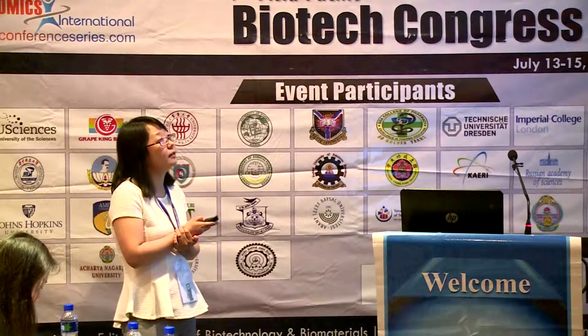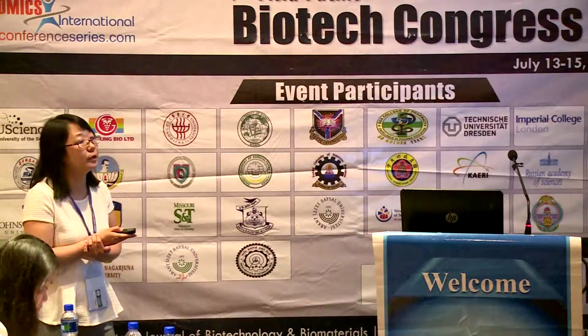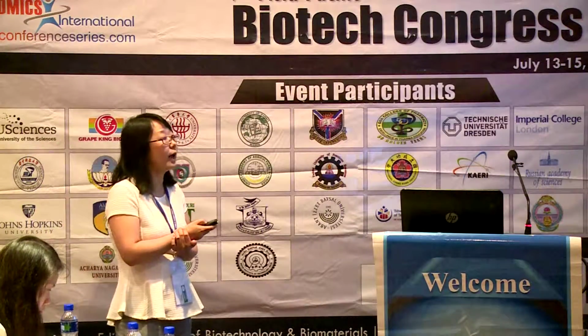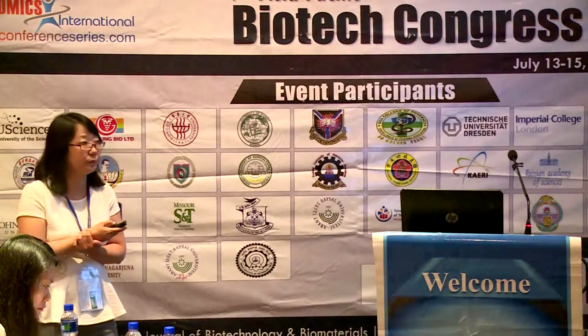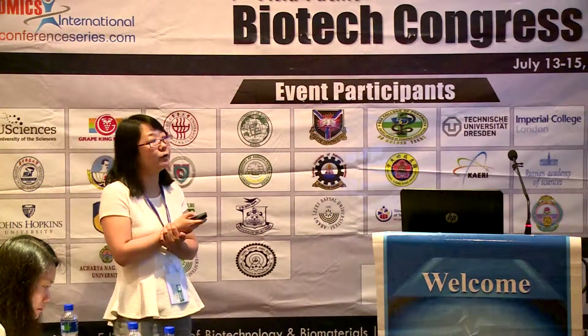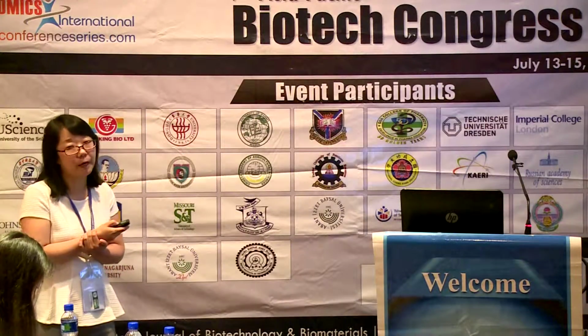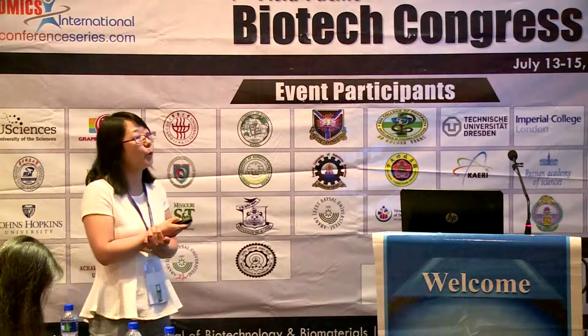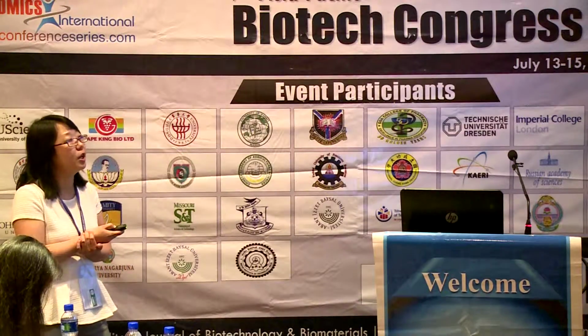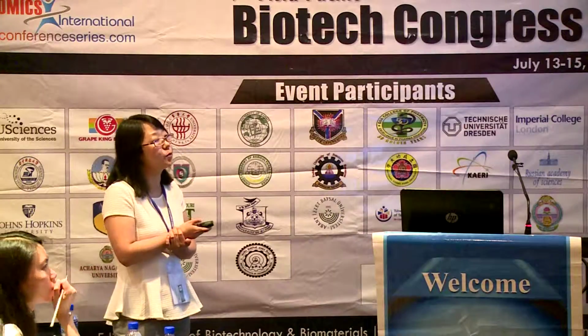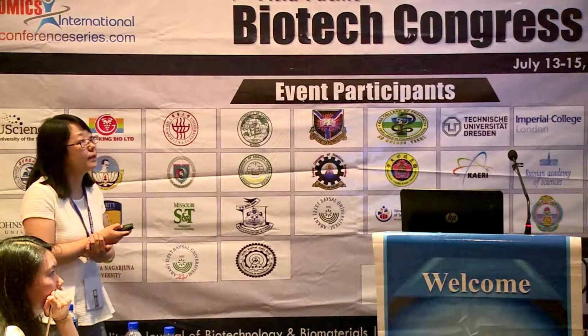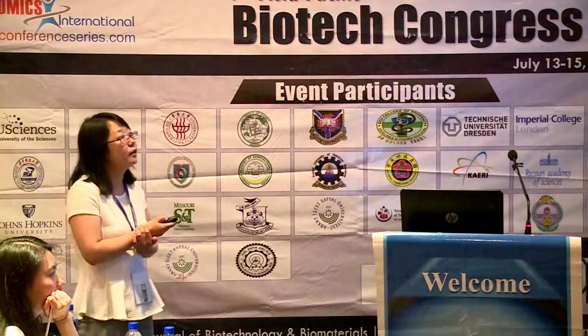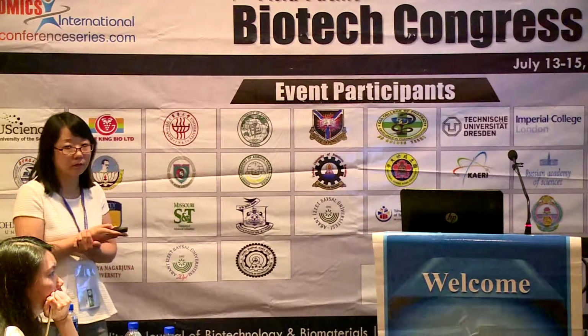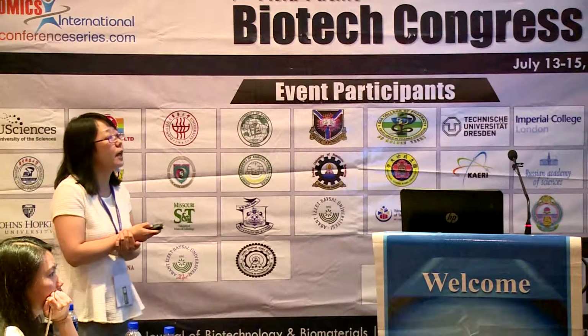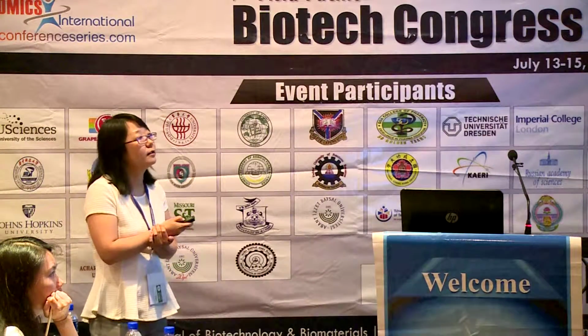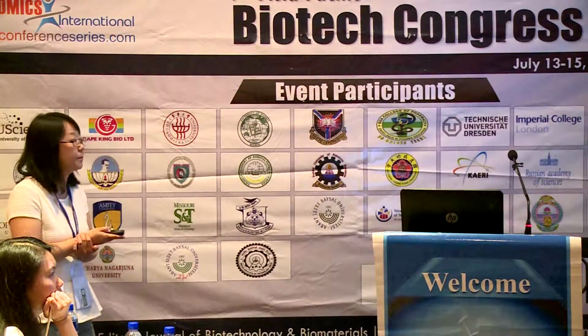First, I tested the self-assembly of gold nanoparticles onto the DNA origami template. I found this is strongly dependent on temperature. When the annealing temperature is just 25 degrees, I can barely see any gold particles attached to the origami. However, when I increase the temperature to 37 degrees, we can see some gold nanoparticles attached to the rectangle origami. And when the temperature increased to 47 degrees, almost every origami has gold nanoparticles. At 47 degrees, the yield is almost 100%.